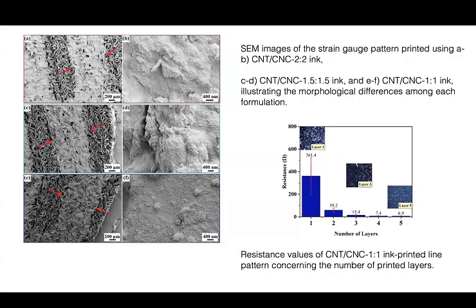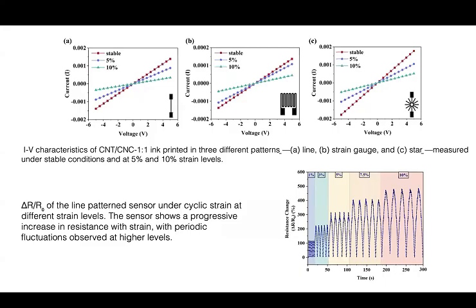How many layers? You can put 10 layers, no problem. But what's going to happen with the textiles? You have a rigid surface on top, which is going to behave separately. So it's not going to work with the textiles underneath. It's going to be a completely different body. So we are trying to avoid it. It should be soft enough that it will also damp and accumulate the response of the textile structures. In our case, it is a knitted structure.